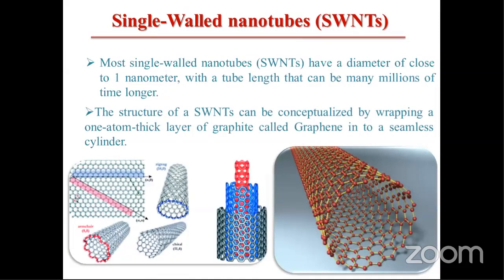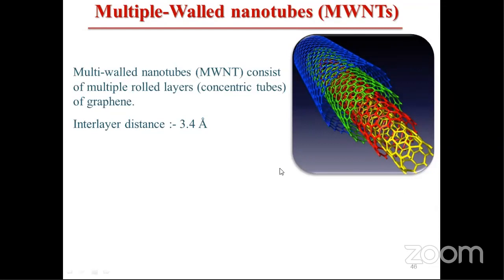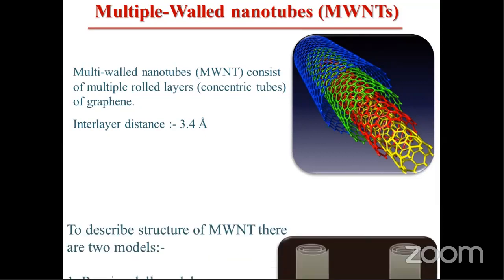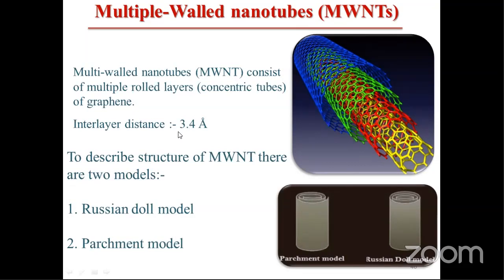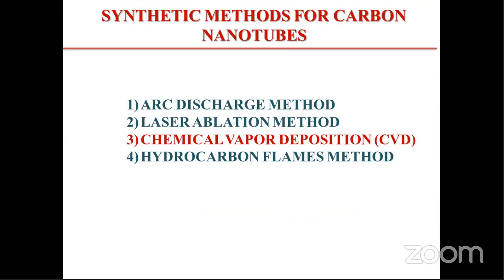The structure of a single-wall nanotube can be conceptualized by wrapping a 1 atom thick layer of graphite called graphene into a seamless cylinder. That is, you take a sheet, roll it, and you have a single-wall carbon nanotube. Whereas multi-walled has multiple rolled layers, or in other words, concentric tubes. The interlayer distance, that is the distance from one layer to the other, would be around 3.4 angstroms. So these are the two models, the parchment model and the Russian doll model, in the case of multi-walled nanotubes. These nanotubes, as I was telling you, can be synthesized by 4 methods: arc discharge method, laser ablation method, chemical vapor deposition method, and finally, hydrocarbon flames method.